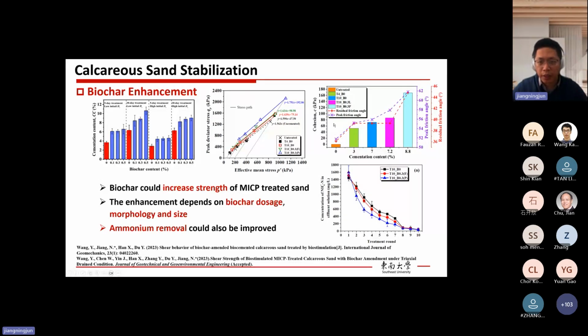And from it, we could get cohesion. If we compare cohesion for these three cases, no biochar, needle-shaped biochar and powder-shaped biochar, then definitely the powder-shaped biochar leads to more cementation and higher cohesion. Then it's the needle-shaped biochar. And finally, the smallest one is the biocemented sample without biochar.